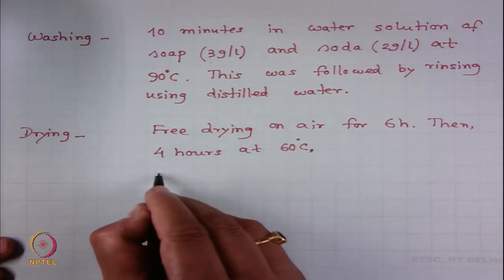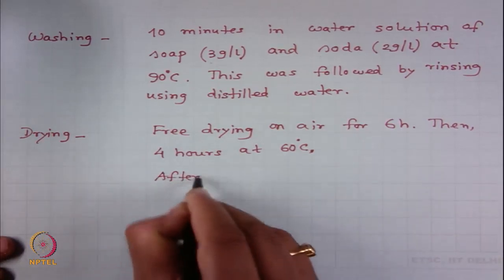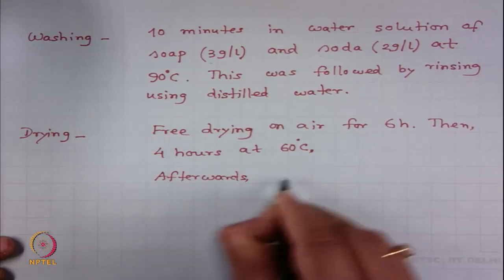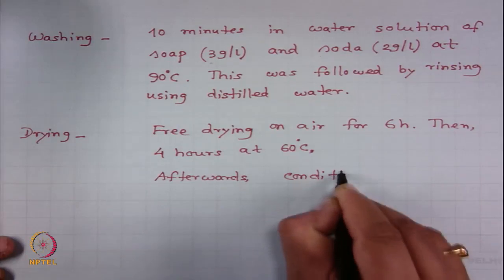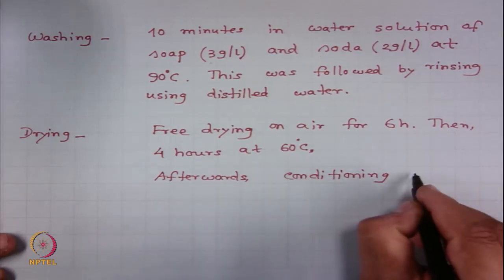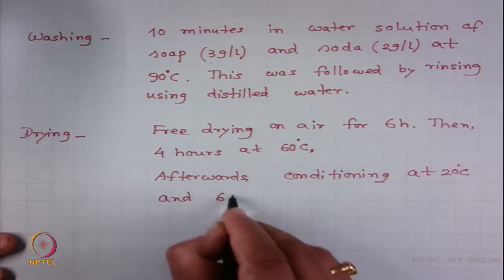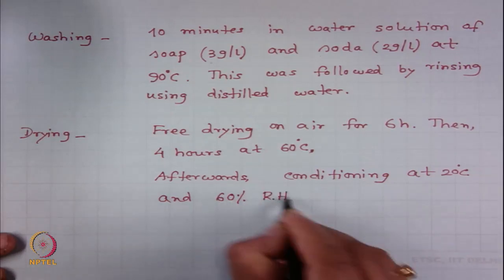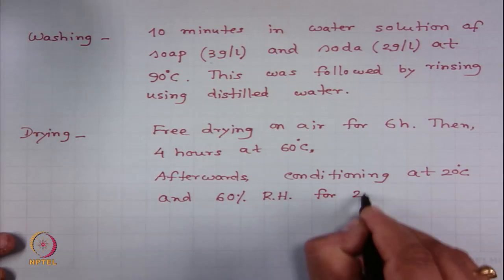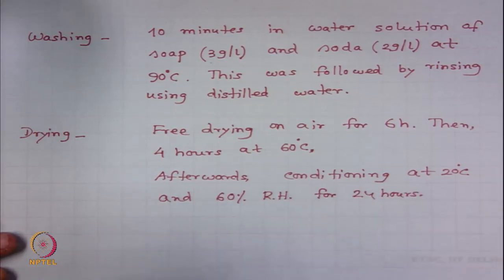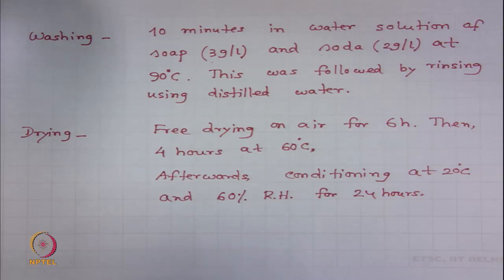After that, conditioning at 20 degree Celsius and 60% RH for 24 hours. So, this is how the experiment was carried out and we measured the shrinkage and we obtained the results. I will show you now the results.